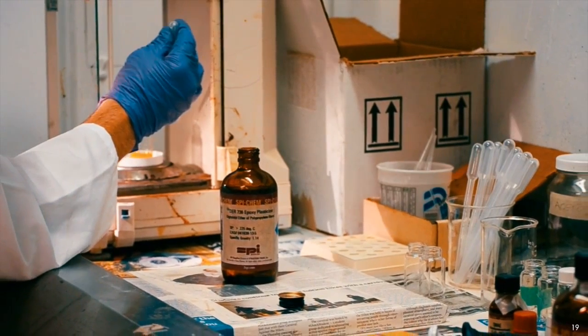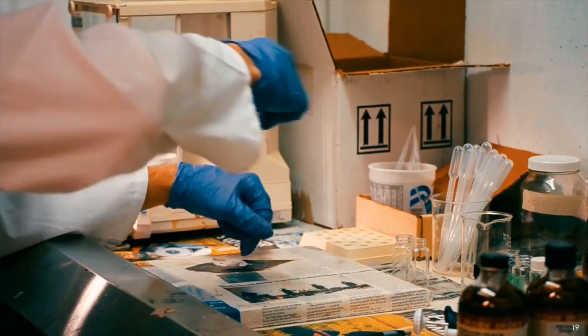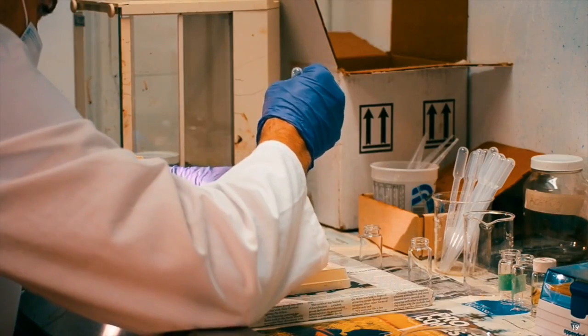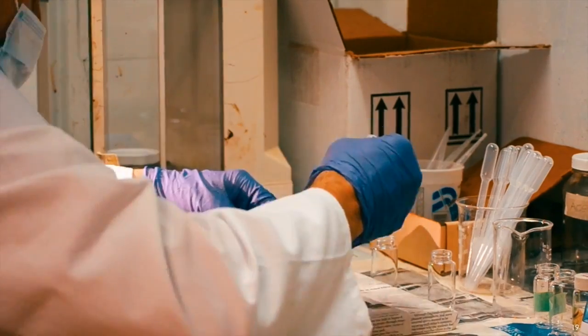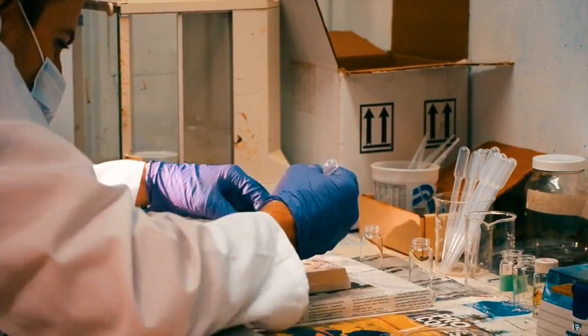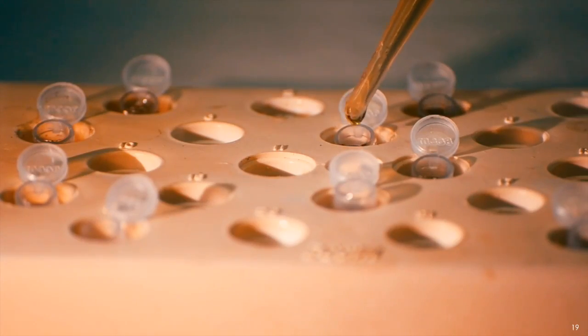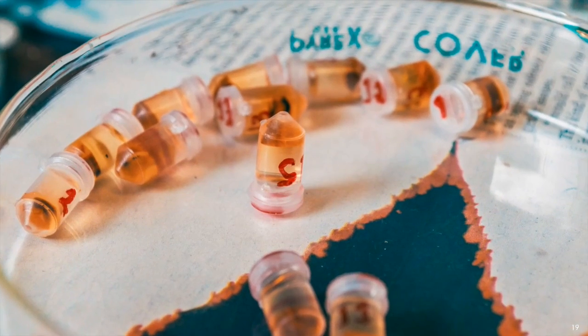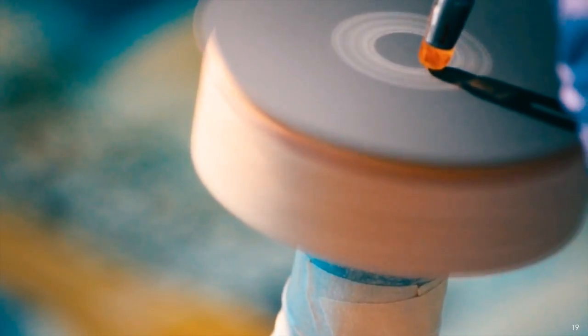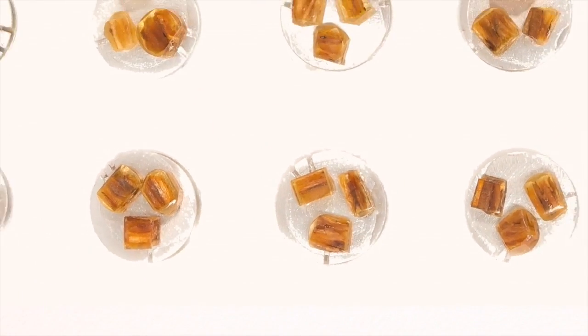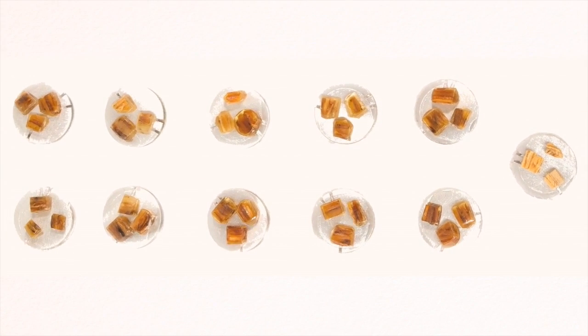So after they were treated, I took small specimens from those samples and embedded them with a low viscosity epoxy resin under vacuum and pressure. Here is the process of embedding the specimens with the resin. And after curing them in an oven to harden the resin, we could sand and polish their surface without altering their original structures. We had 5 replicate samples from different panels for this technique.